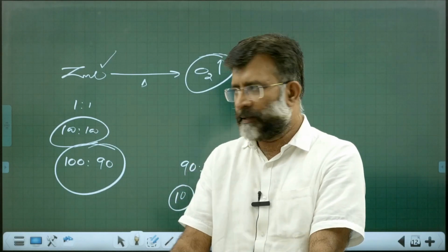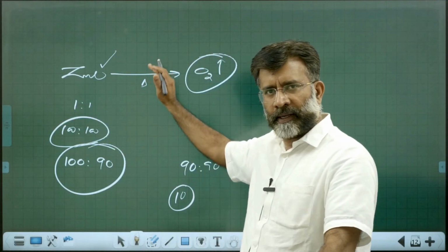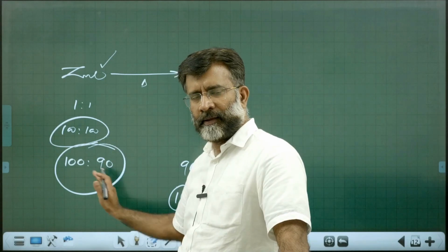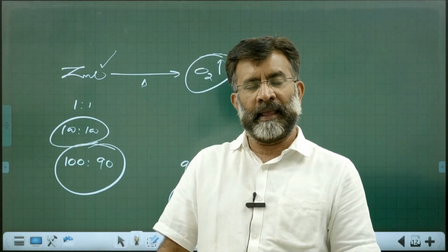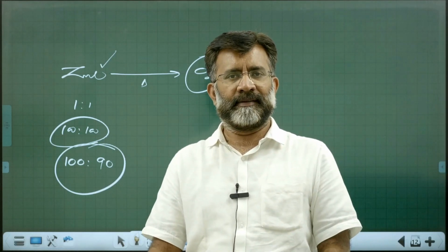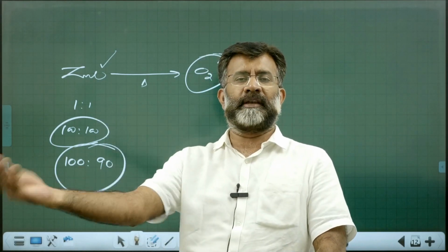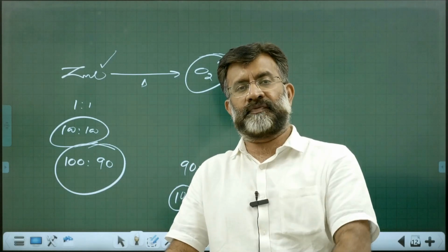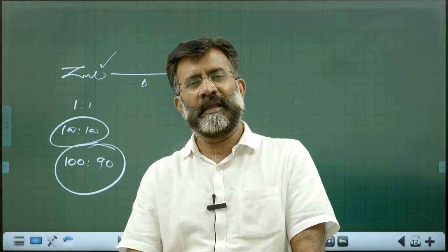So I repeat, there was 100 zinc and oxygen. Upon heating, some 10 oxygen escaped. Now you get 100 to 90. Now this crystal reorganizes. You get a 90-90 crystal and 10 extra zinc trapped into vacant sites, voids. And the corresponding electrons are trapped in the nearby voids. That void electron trapped acts as an F center, and the white powdery zinc oxide becomes yellow in color.